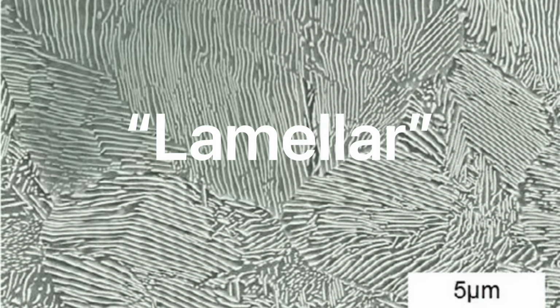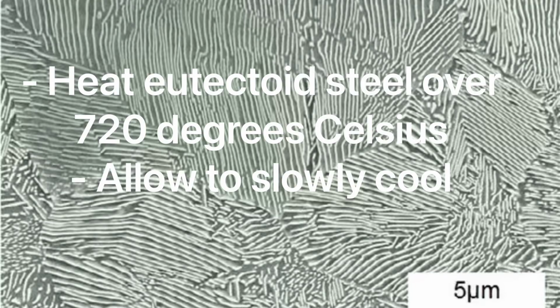The microstructure of such a steel consists only of perlite, and, when viewed from a microphotograph, it appears to be laminated due to the large amount of tiny lines within the photo, leading to the term lamellar. Perlite is formed by heating a eutectoid steel over 720 degrees Celsius and then allowing it to slowly cool. Perlite is actually a two-phase structure, composed of layers of cementite and ferrite.